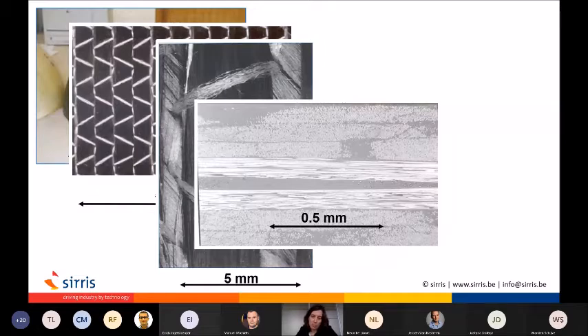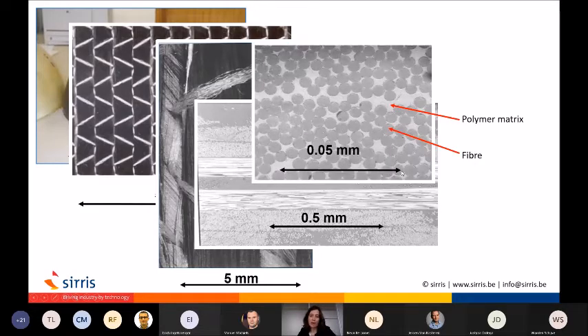When you cut the composites and you look at the cross section, then you see all the fibers. These are circles because we are looking at cross sections. So you can see the fiber bundles in several directions. So this is a fiber that is in 90 degrees on the screen. This is a fiber that is along the screen surface. So this is a zero direction fiber. But basically, when we talk about composites, we are talking about a blend of a polymer, which needs to be very much next to the fiber, and we don't want any porosity next to this fiber. And this is very important when we start talking about manufacturing.